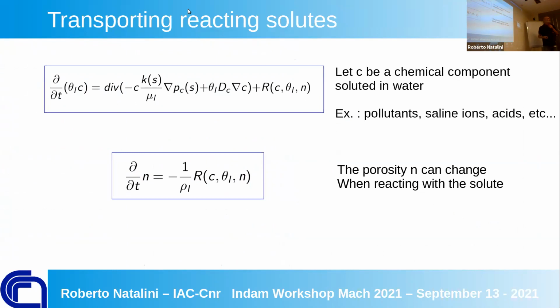The other ingredients, because we are speaking about a reaction in flowing media, is the fact that some chemical component is flowing. This chemical component has a speed given by the water. But also there is a diffusion of this, as previously, you remember, for the pollutants inside of the surface models. Even here we have a diffusion of the pollutants inside of the water, and we have the reaction term, which is characteristic of this kind of problems: the porosity is not fixed. Porosity is changing during time.